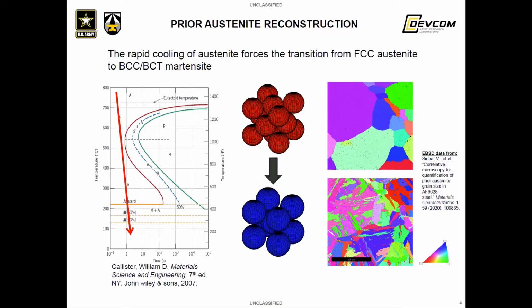Looking at the martensite lath structure in the bottom, your eye might be drawn to where this inverse pole figure mapping, where the coloring shifts. Often, but not always, these color shifts correspond with the boundaries between the pre-existing austenite grains, which you can, in this image, confirm by looking at the top image there. But again, that rapid transformation is called the martensite transformation.